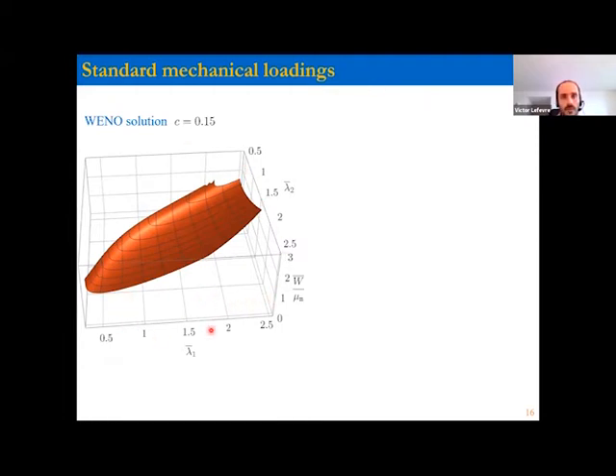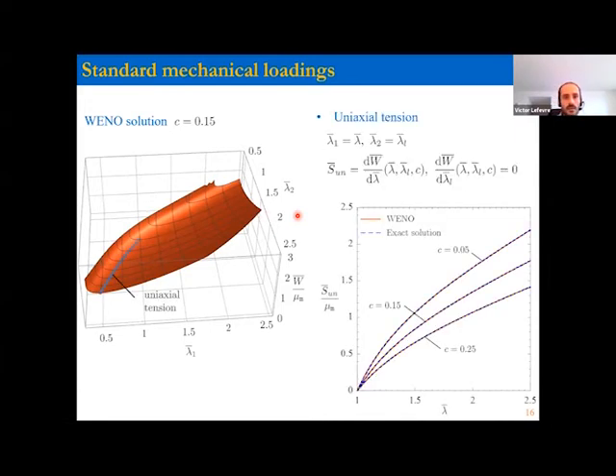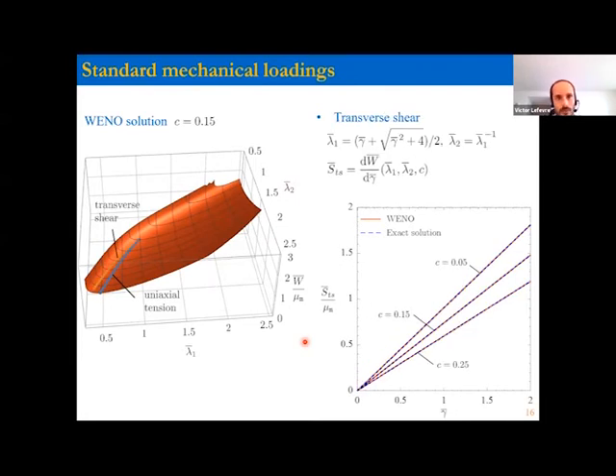So that's what it looks like. So it's 15% porosity for this composite, as a function of the two principal stretches, lambda 1 bar, lambda 2 bar. And then you can follow any loading path that you want. So this is for uniaxial tension. You follow this line, you compute the partial derivatives, and you get the stress. So you see here different volume fractions and a very good agreement between the exact solution and the prediction from the scheme. That's another loading, for instance, transverse shear, and the same thing. You follow the path, compute the derivatives, and very good agreement there as well.